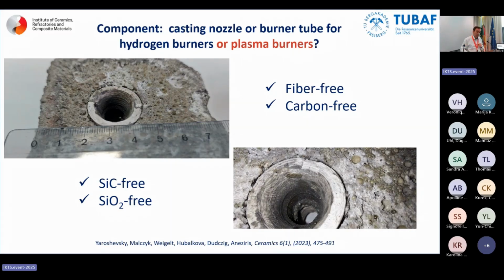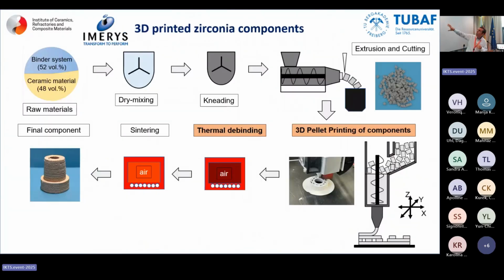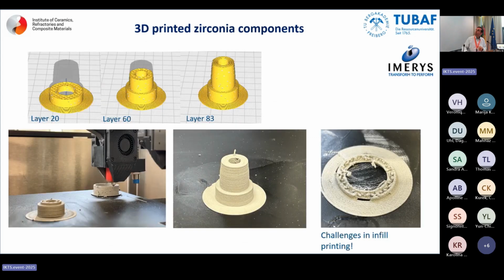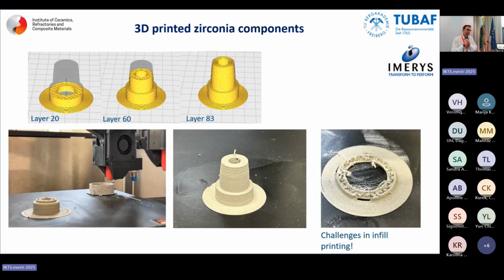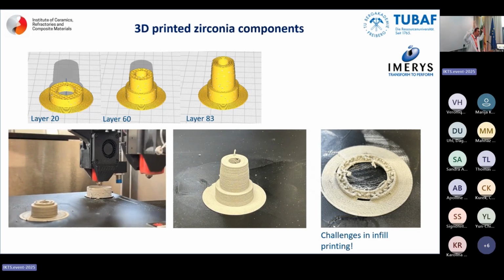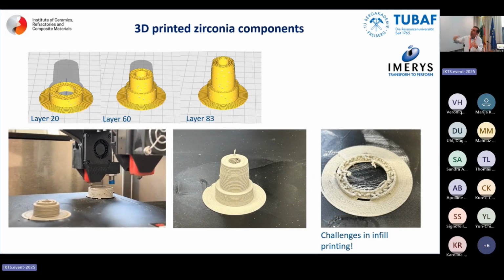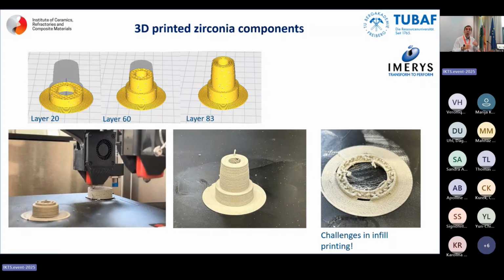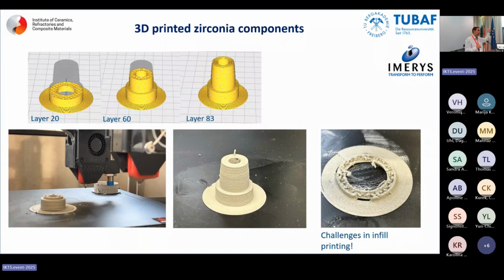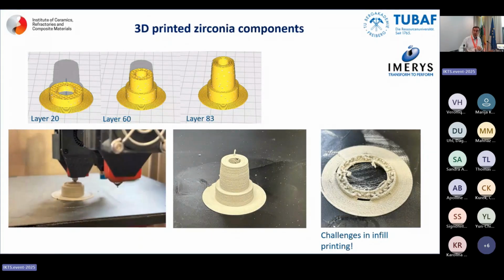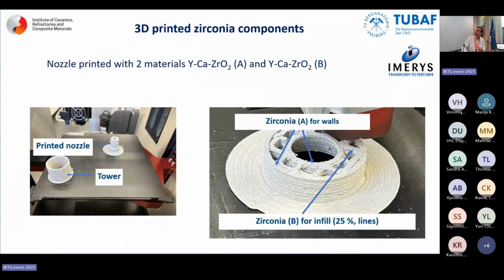And yes, if you survive, is it perhaps a material or a processing route for hydrogen burners or for plasma burners? Plasma burners we will see immediately. And somebody would say, is the technology very difficult? No, it's the normal ceramic technology as we know it when we make extrusion with filaments, and then we go to printing and debind pieces. Some pictures, yes, you can play and you can use artificial intelligence to create structures, and it's fantastic, but it should have a meaning: how many layers you do, why you do it, and keep in mind costs, energy, and so on. And at the end of the day, you want a functional product.